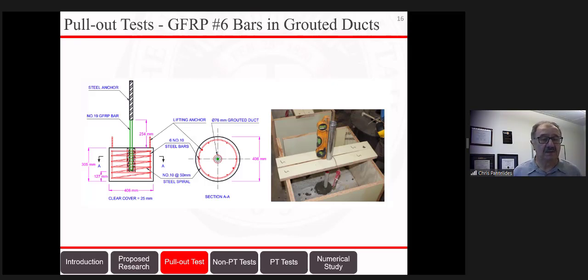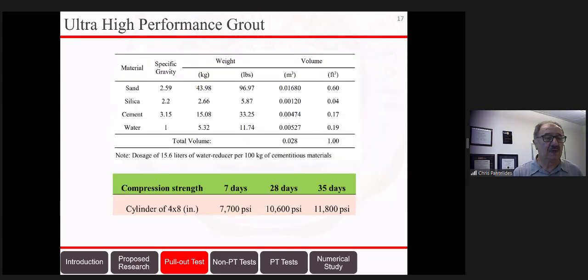So we constructed some cylinders made of concrete that you can see here of varying lengths and varying embedment depths. And we tested them for pull-out strength. We used the same type of grouted duct that we use in the large experiments. And this is where we developed the ultra-high performance grout. And you can see this grout developed 10,600 PSI in 28 days and higher strength than that. So the main components were silica, sand, cement, and water.